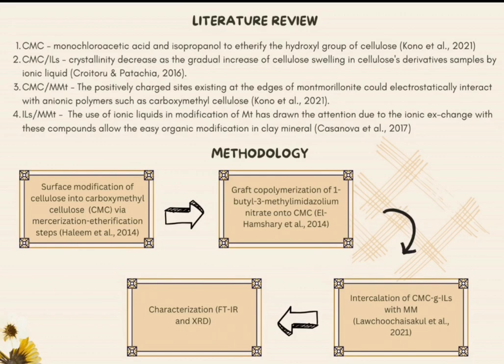The methodology in the study involved four steps. First, surface modification of cellulose into carboxymethyl cellulose via mercerization and etherification steps. Second one is the grafting technique between ionic liquid and CMC. The third one is integration of MMT into CMC. And lastly is characterization of the final product.